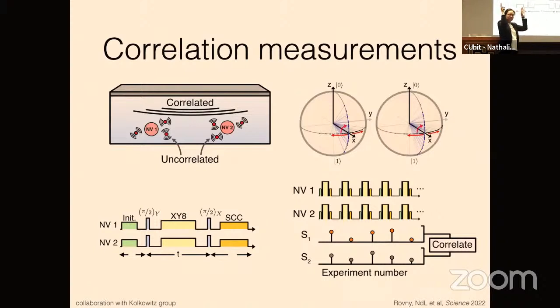doing a population measurement directly back onto the z-axis, what we can do is a pancake pulse where we flip it like this. Now that gives you maximal sensitivity, but you would normally not want to do this for single NV measurements because then all of your measurements would average out to 0. But now, because we're looking at this higher order moment and we're looking at this covariance, this is the thing that you want to do. Okay, so otherwise this is all the same as what everyone would do, but this is a Ramsey where we do this and then let the things fan out and then flip it like this. And then the idea is we now save all of the traces, save all the data, and then we just compute a correlation between the two different NV centers.